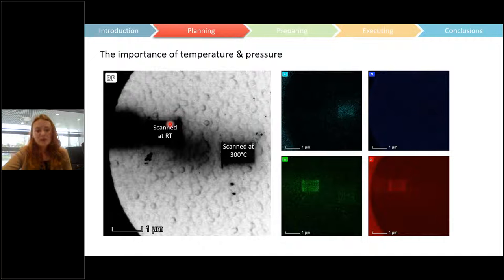But when we did EDX on these particular areas, we noticed something important. So on the right, you can see the EDX maps for the different areas that we've scanned. And as you can see, the nitrogen is everywhere. The carbon, however, is only after 300 degrees scanning. So on the right-hand side, that area of contamination corresponds to carbon. But when we scanned at room temperature, we had this enormous thick layer of something appear. And what we realized is that that something is silica.